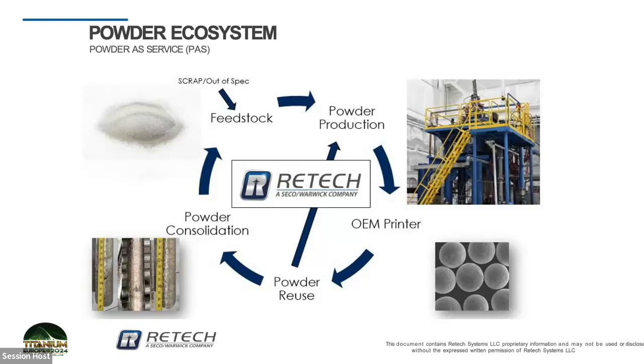And so, if I were to wrap the talk up into an overall summary, the PGA and the consolidator allow us to create a holistic cyclical process where we take low-cost feed, we introduce that feed into a plasma hearth melt that has a fairly high melt rate, then produce powders at scale, and then take that powder, print with it or use it in other applications like MIM or HIP, and then take any oversized powder from that process, put it right back into the recycled stream, consolidate it, and then take oversized powder or ingot, in this case, back into the atomizer. This allows us to really have that flexibility and closed loop, minimize our overall cost of the process, decrease the energy consumption, and hopefully increase the adoption of titanium powder across our industry.